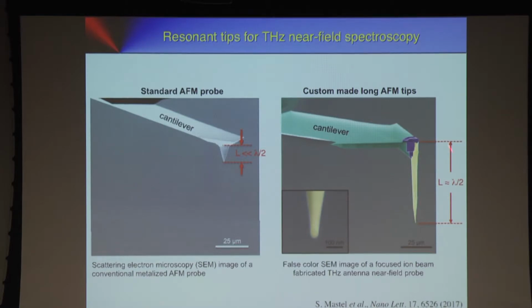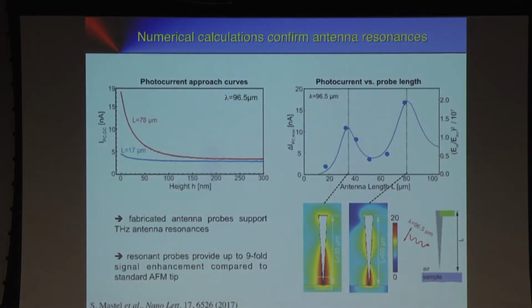And so student Stefan Mastel did this by FIB fabrication, a rather sophisticated technique. He cuts away the standard tip. He cuts out with FIB a long metal wire up to 100 micrometer long. We can make it as sharp as 10 nanometer or even better. And we can adjust the length. And then we can do AFM and we can do imaging. And we can actually get these resonances.